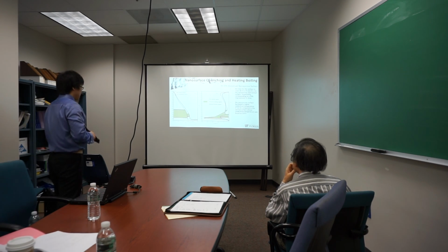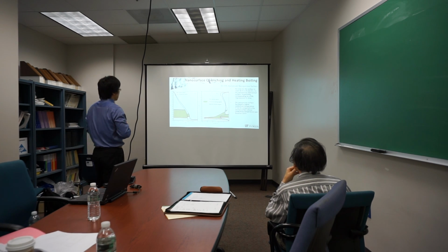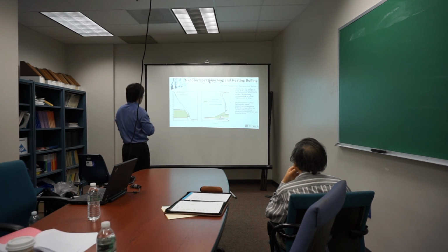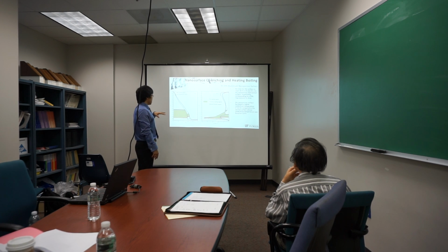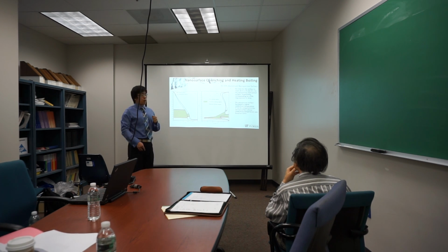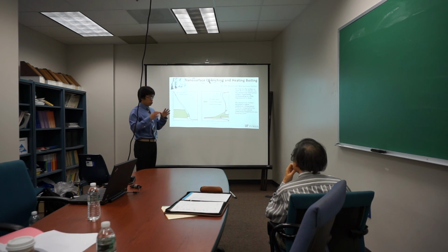This is a quenching curve we got on the 99.99 aluminum alloy surface, which I did last year. What we can find here is that the nano surface actually works, and a very important thing is that it pushes the Leidenfrost point up by around 30 degrees Celsius, from about 120°C to about 150°C. It's a lot, and it also gave us about 3 times higher critical heat flux.